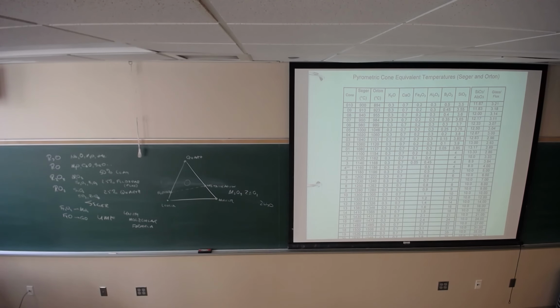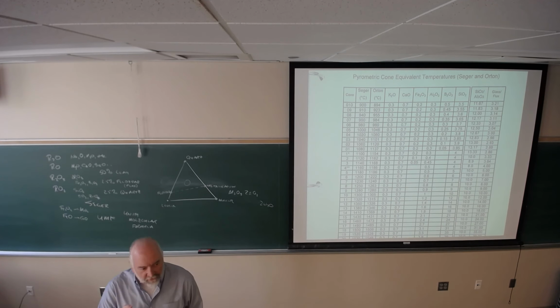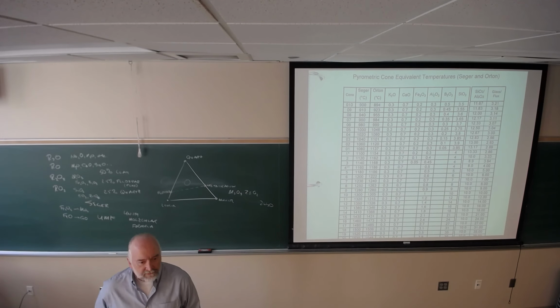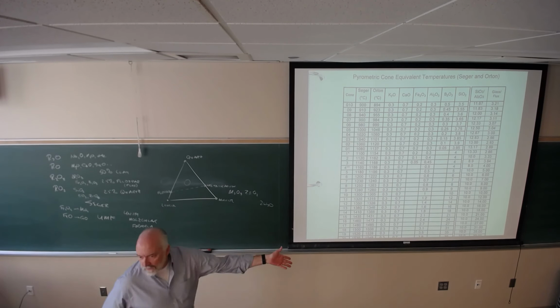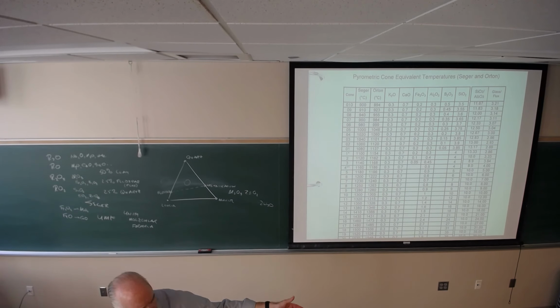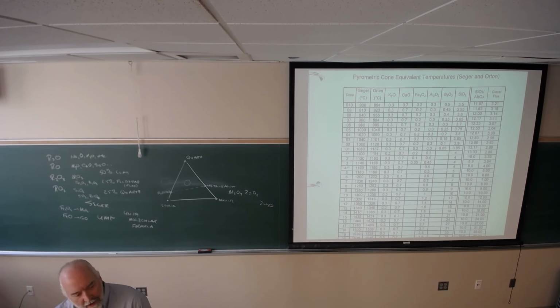This is essentially 2 by 2, and it's been polished. And this material, though, is fast fire. Cold to cold for this material in 50 minutes, which is staggering. For electrical insulators, heating cycle times are from about 36 hours to 4 days, 96 hours. They fire this in less than an hour. Ceramic tile, not porcelain, 38 minutes. There is nothing sane about that.